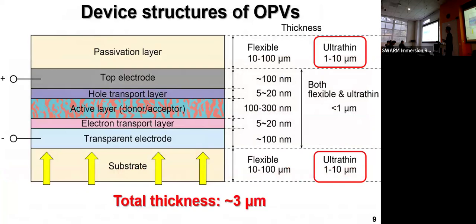Okay, then here I would like to show you the structure of the OPV devices. We normally use 5 functional layers. The first is the transparent electrode, then the electron transport layer, then the active layer. Normally we are using donor-acceptor organic material blend systems. This is the photo-absorbing layer. Then the hole transport layer. The last layer is the top electrode. Normally we are using an opaque silver electrode, so we could make non-transparent organic solar cell systems.